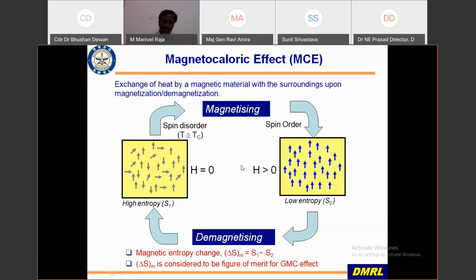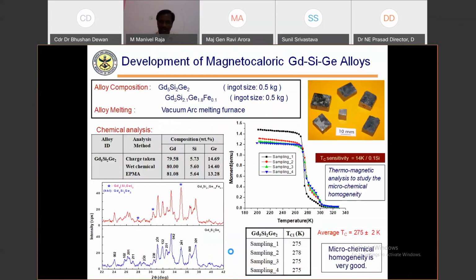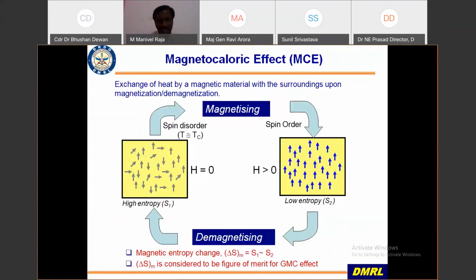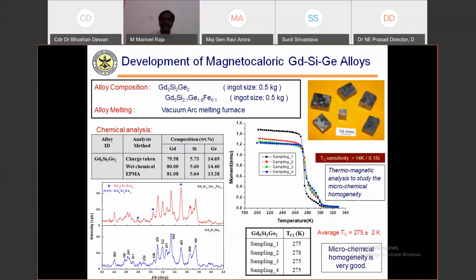The material should have a large change in entropy when you apply a magnetic field. That is the figure of merit for this class of material. DMRL is working on this material technology. This material is based on rare earth alloys, gadolinium, silicon, germanium alloys, and this is the composition of this alloy.